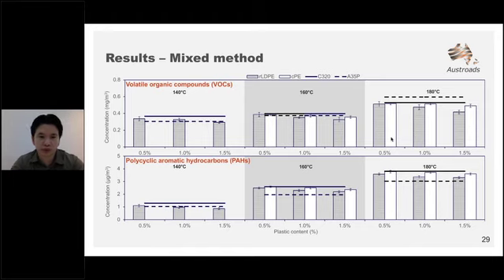And it's no surprise that the higher working temperature increases overall emissions for both VOCs and PAHs. If you look at the 3 different columns, you can already see a spike as the temperature goes up. Increments up to about 100% for VOCs and about 200% for PAHs when temperatures were increased from 140 to 180 degrees Celsius.